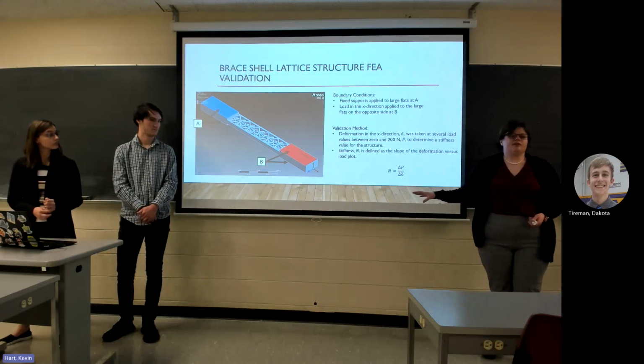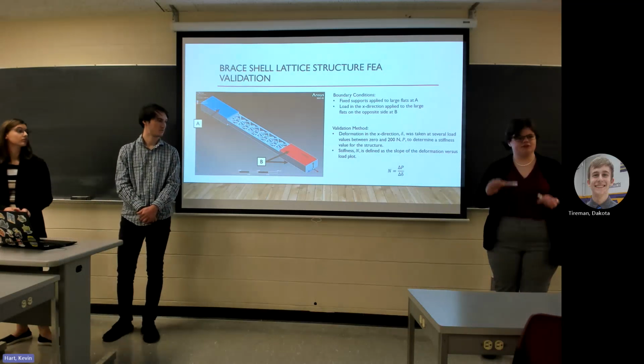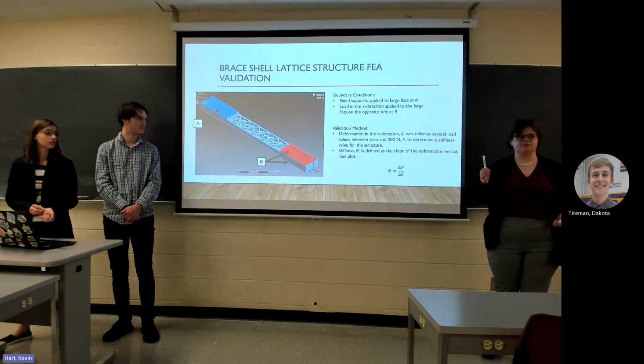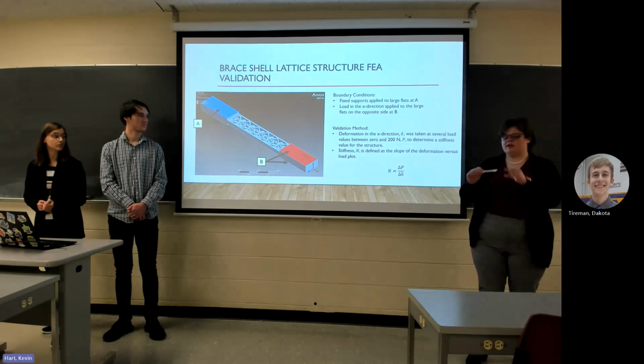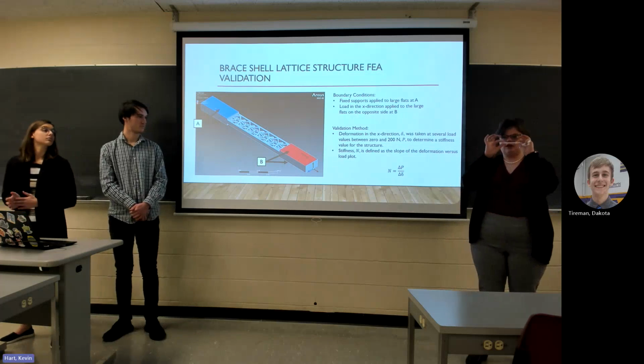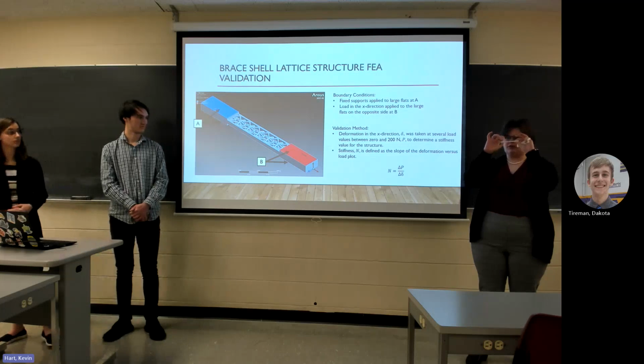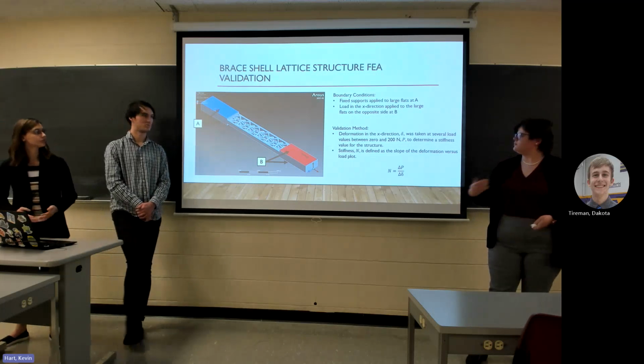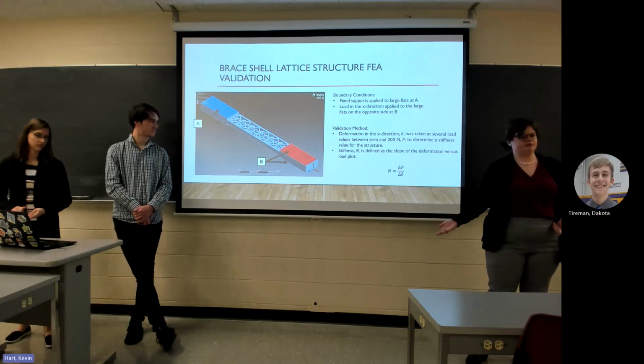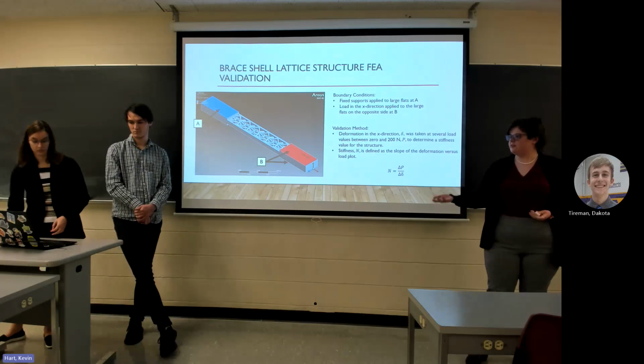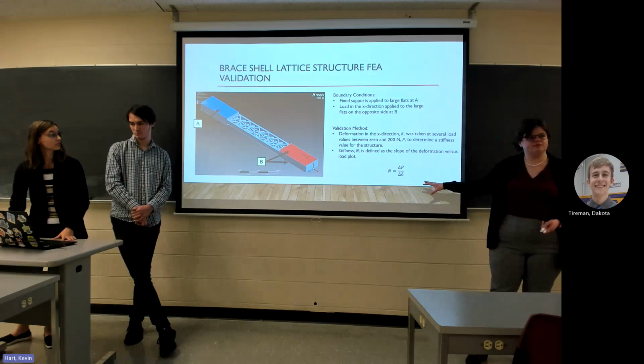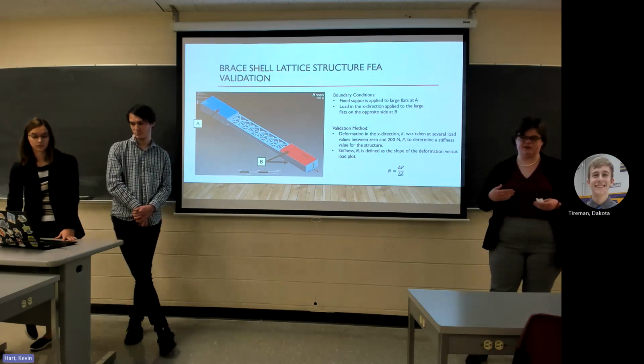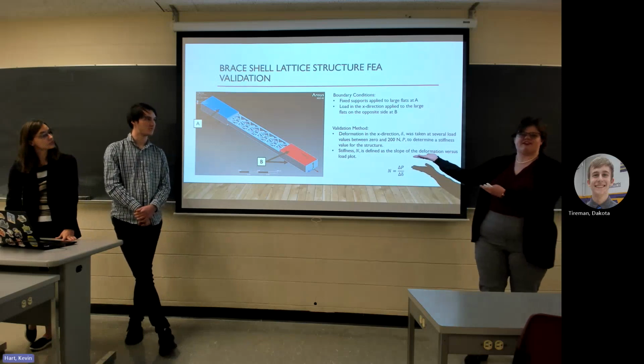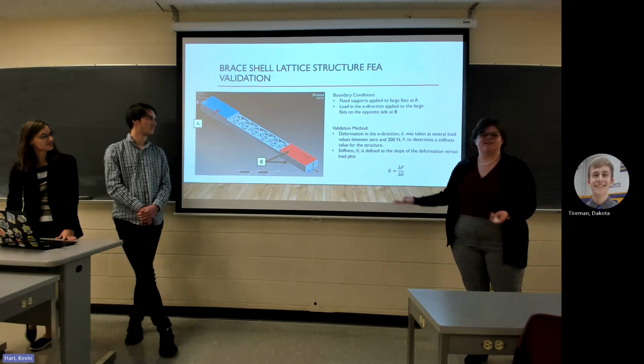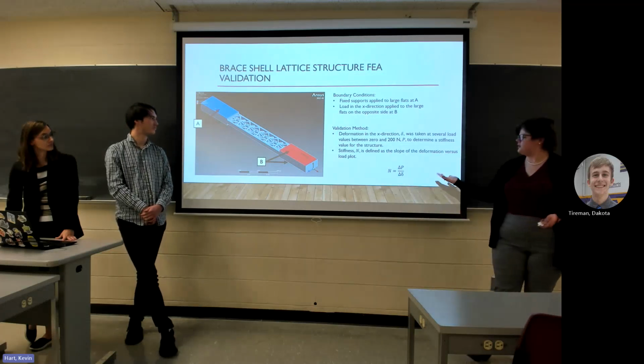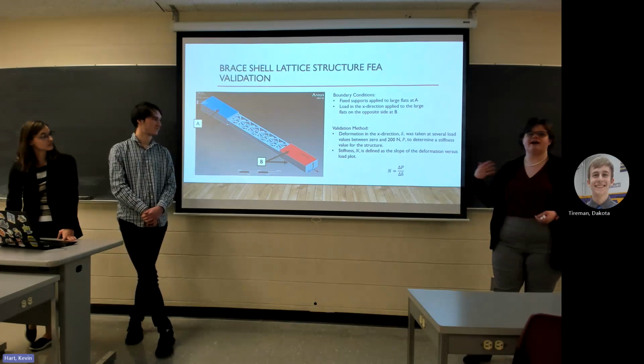So we are validating these models based off of tensile tests. So we have these tensile test specimens and models for each of them, where we have fixed constraints on these two surfaces and a force pulling on these two surfaces to mimic a tensile testing machine. From experimental data that was generated previously, we have deformations and loads to create a stiffness. We're using a stiffness because of the difficulty in figuring out how do we define stress? How do you define stress on this from a tensile test machine? It's not a material, it's a structure, right? So this stiffness parameter is what we're going to be using. We're looking for high stiffness for the brace shell.